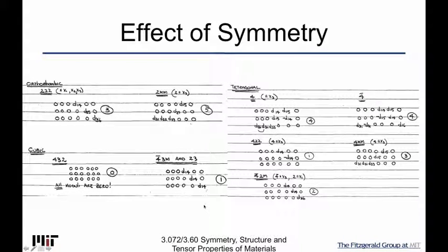Continuing on, we have the higher coordinate systems here. Orthorhombic case, where we put the twofold axes parallel each one to x1, x2, x3. Now you're talking, because you can see that to make under those transformations, all of them, right? And remember we did an example before, we put one twofold axis, we put the second twofold axis, and it kills a lot of the zeros. So now you only have 3 of these to worry about.